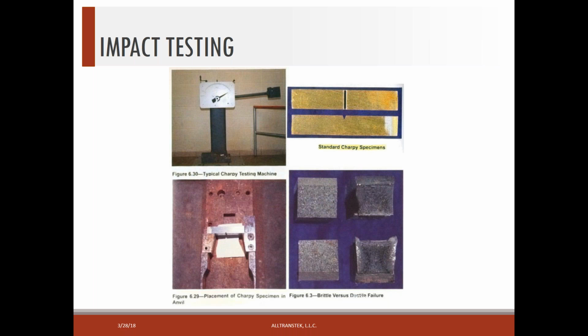And then in the lower right-hand corner, you see 2 types of fracture. The one on the left is a brittle fracture, which is usually undesirable because that means there was very little energy taken to break that particular specimen. The specimen on the right is referred to as a cup and cone fracture, which is more of a ductile fracture. And you may be saying, well, what does all this have to do with it, and why does this really matter?